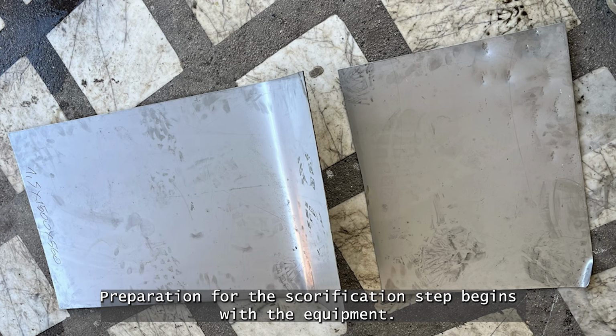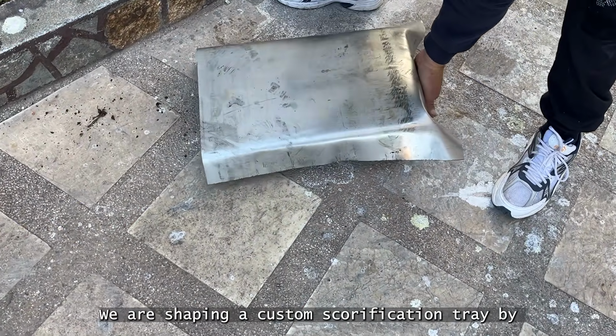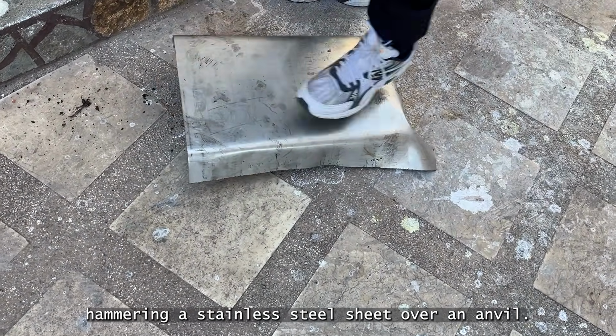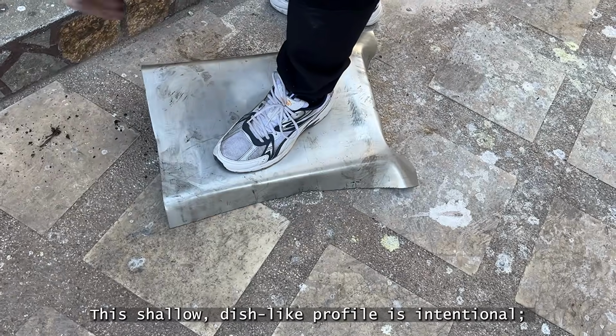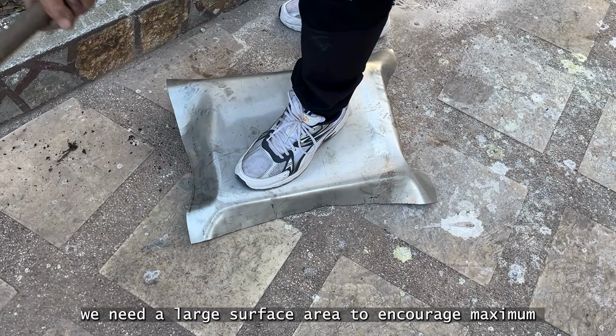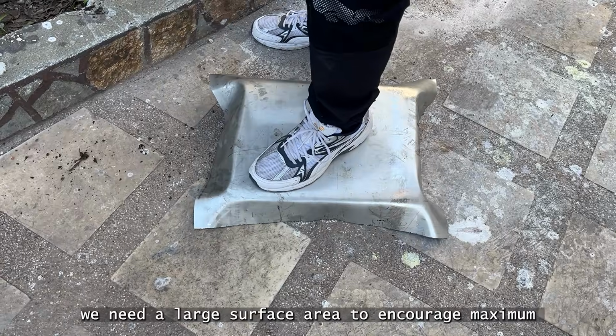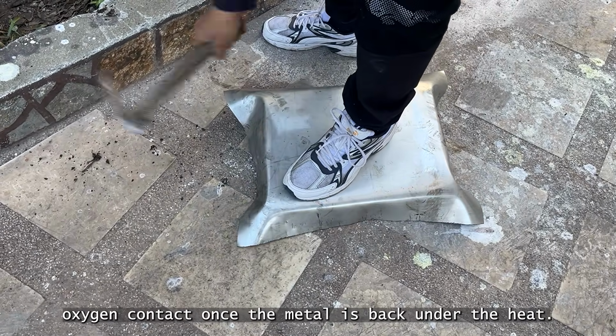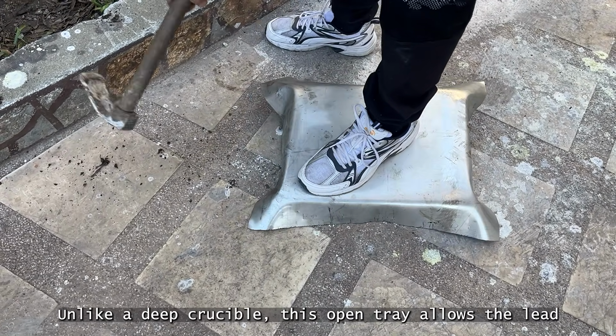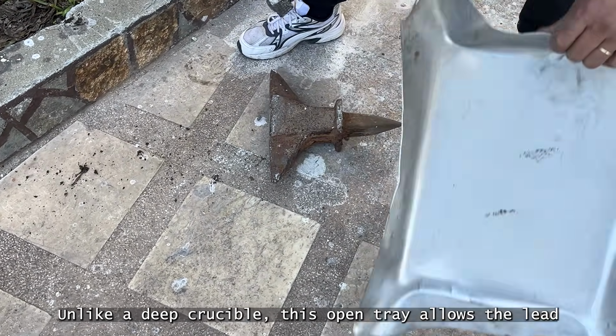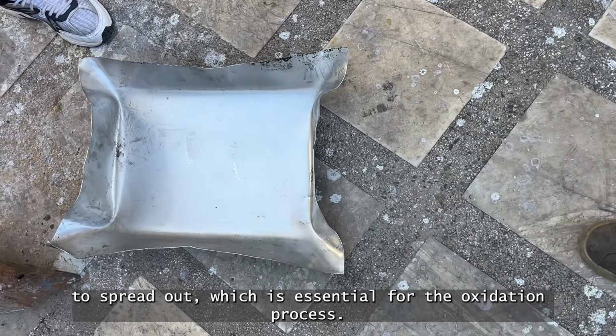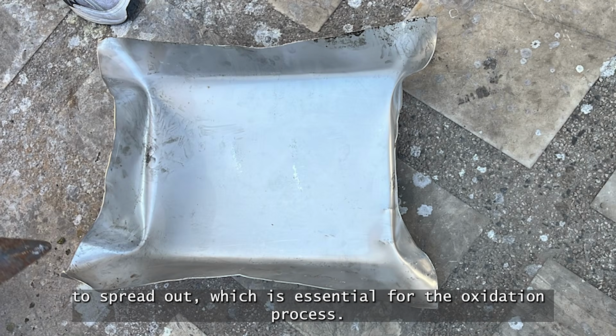Preparation for the scorification step begins with the equipment. We are shaping a custom scorification tray by hammering a stainless steel sheet over an anvil. This shallow, dish-like profile is intentional. We need a large surface area to encourage maximum oxygen contact once the metal is back under the heat. Unlike a deep crucible, this open tray allows the lead to spread out, which is essential for the oxidation process.